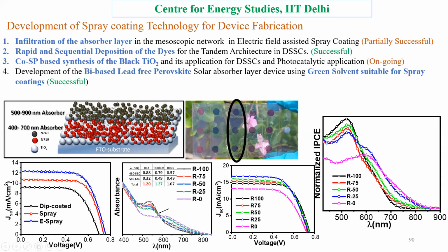So this way I can make a tandem device, and this is one photograph, that this is the black dye and this is a tandem device. We can clearly see that it seems very blackish in color, and it almost absorbs all the light, and it also has good electronic properties. So this is the absorption of that material. And normally, for DSSC, efficiency is quoted, JSC goes only up to 9 milliampere per centimeter square, and efficiency is around 5%.